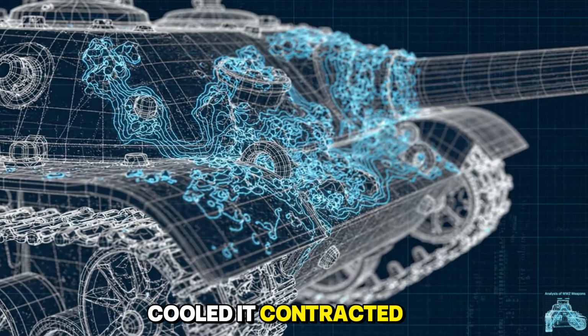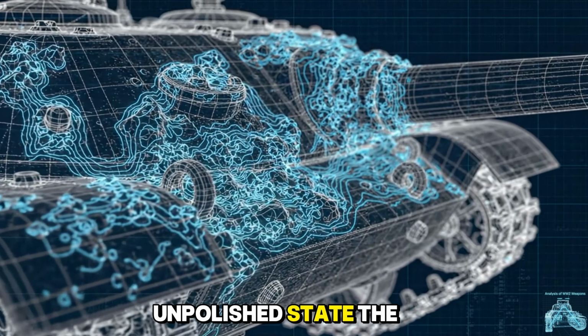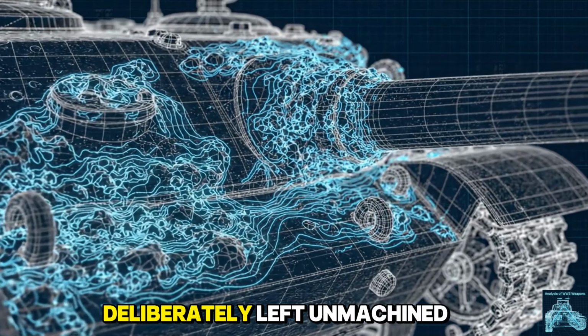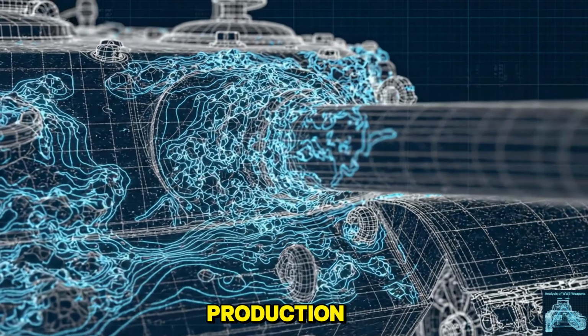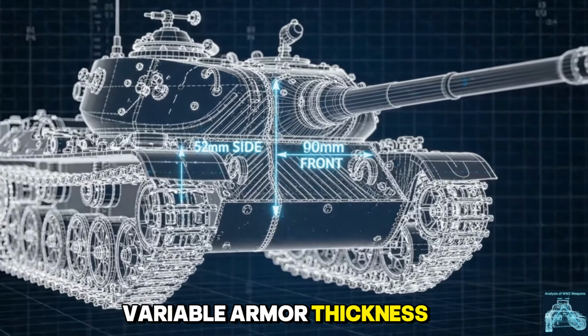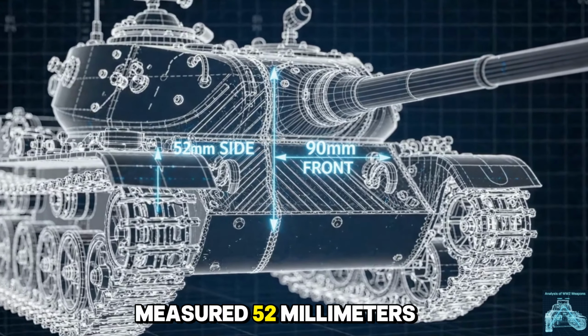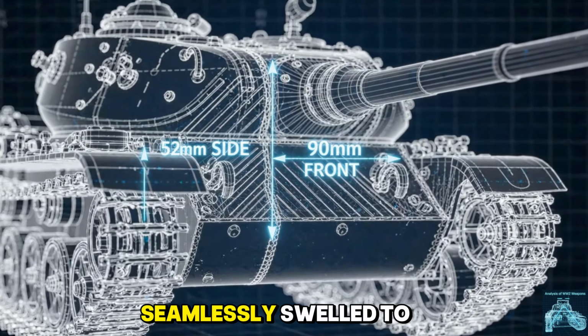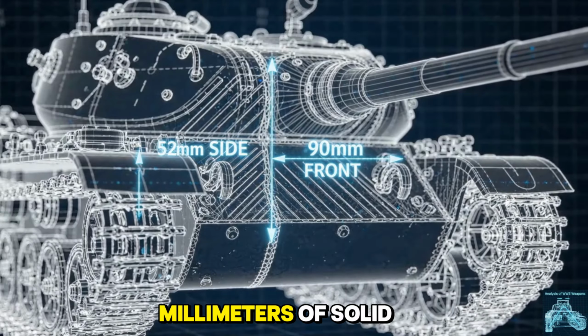As the metal cooled, it contracted into a brutal, unpolished state. The surface was heavily pitted and rough, deliberately left unmachined to accelerate mass production. Casting allowed for variable armor thickness without welding. The sidewalls measured 52mm, while the frontal facing seamlessly swelled to a massive 90mm of solid steel.